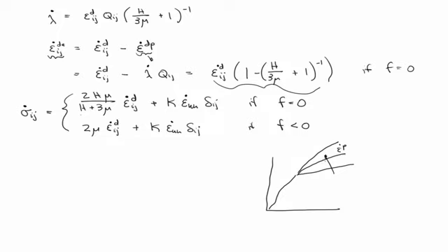What you get is an equation that's nonlinear in lambda dot, and you have to do a local Newton iteration, a local nonlinear solve to find out what lambda dot is, and then you plug it back into the equation. So you have to actually numerically solve for lambda dot in order to update the stress. Okay. And so we'll talk about an example of that.